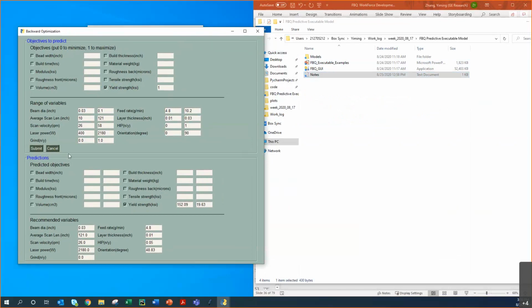Now, the backward prediction and optimization is shown to be done. Like you can see here, the optimum yield strength is identified to be 152 KSI, with the larger uncertainty to be 20. And larger uncertainty is expected because we are trying to find the extreme value, which is usually far from our design point. And the recommended parameters are shown in the bottom figures.